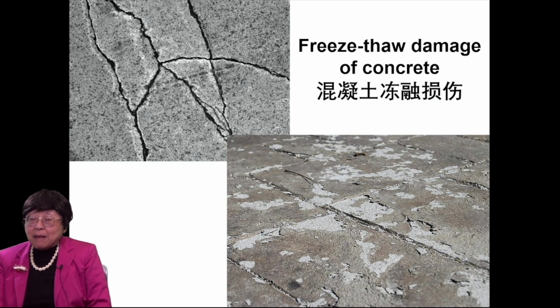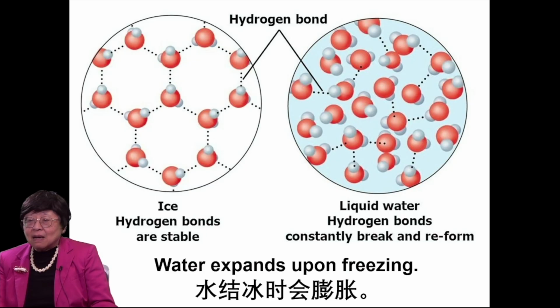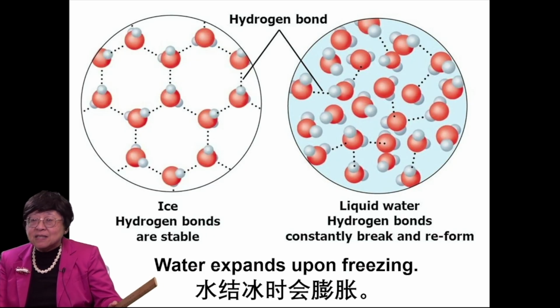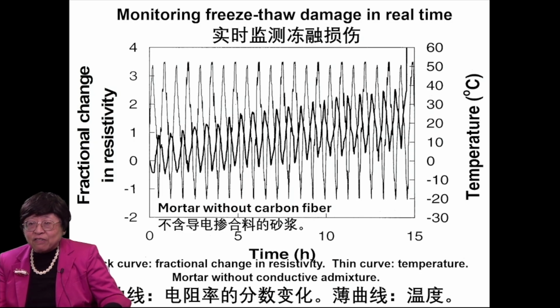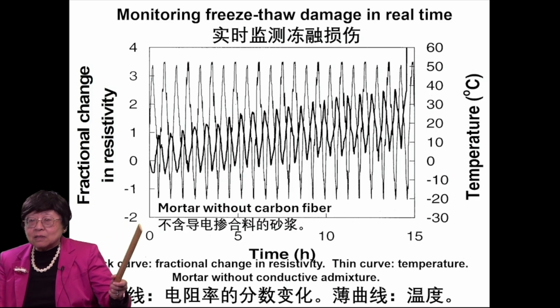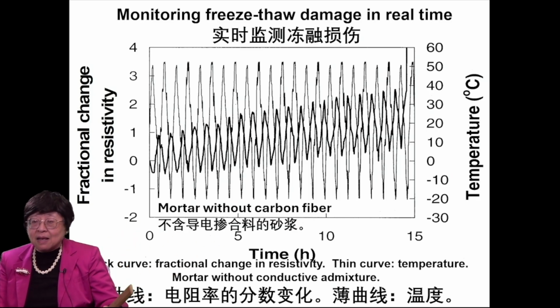Now, freeze-thaw damage of concrete is a very serious problem, because the water expands upon freezing, and inside the cement or the concrete, you have some free water. And so if you have multiple cycles of freezing and thawing, you would have degradation. And this degradation process can be monitored very effectively by resistance measurement.